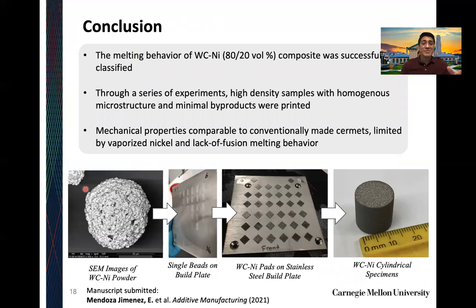So just to summarize, we took a novel composite powder that I have never seen used before. We classified its melting behavior using a simple single beads experiment that only takes about 30 seconds. We then leveraged those results to print 10-layer pads and realized that we were working within a very successful processing region. And through some minor tweaks in the layer thickness, we managed to build up tungsten carbide nickel cylindrical specimens that are comparable to what can be done via conventional means. And this manuscript, we just finished writing up last month, and we submitted it a couple weeks ago. So we're looking forward to having it published in the Journal of Additive Manufacturing.